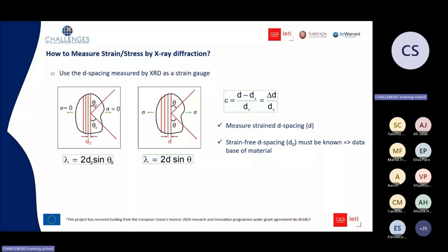This d0 can be extracted from a database of materials, but I will show you that we can also measure this d0 from X-ray analysis. In the practical case, you have a Bragg peak and you measure the Bragg shift from the relaxed position to the unrelaxed position. And the strain is related to the Bragg angle shift through this relationship.